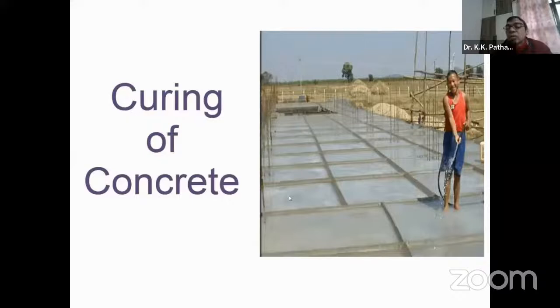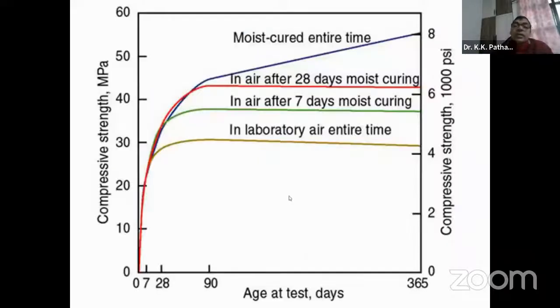Otherwise strength deterioration will be very high. At least 7 days curing must be there. It should be extended to 14 days, but at least the first 7 days curing has to be properly there. Otherwise, research says that if there is no curing, about 30% of the strength will be lost.